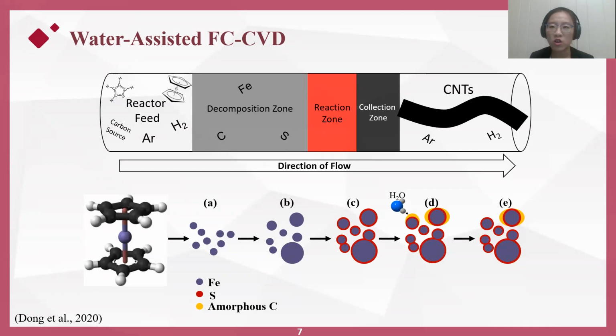Although still somewhat controversial, one of the most widely accepted mechanisms for the FC-CVD process begins with the iron-containing precursor, ferrocene, decomposing at high temperatures to release the iron atoms, shown in the middle, and they form nanoparticles of different sizes after interparticle collisions and agglomerations. Similarly, the red sulfur atoms were released from the thermal decomposition of thiophene, which is another component of the catalyst solution. They bind and coat the surface, which inhibits further catalyst particle growth. Until this step, we have a typical active catalyst particle for the CNT growth.